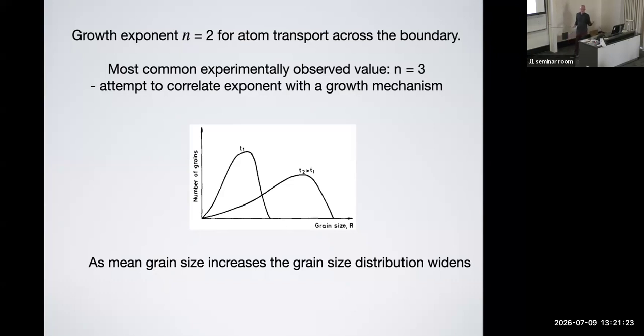And then, of course, as I said, secondary phases, if you have melt or other things present, those are all factors that affect your grain growth rates. So in the end, you have to do experiments on each material to determine actually the growth exponent n and the growth constant, right? That's especially the growth constant also includes, as I said, the activation energy, which is different for every material. The interesting part for the lower mantle is that the grain growth is a diffusive process. So from the grain growth experiments that I'll show, we have some idea now of activation energies in the lower mantle for diffusive processes.